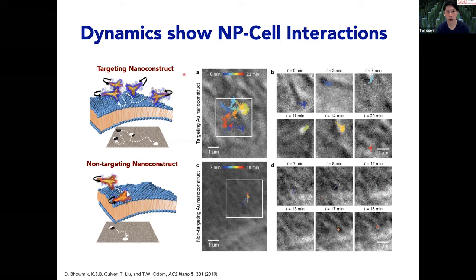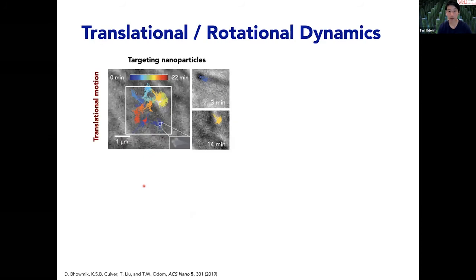And I should also mention, which is quite interesting for these anisotropic particles, that these targeting and non-targeting constructs have the same protein corona profile. So there's this idea that once you put these into cells, the protein corona might deleteriously affect the exquisite nanoengineering of the particle. But it turns out that it's not the case for these anisotropic particles. It's different if you have symmetric particles, which we're finding out now.